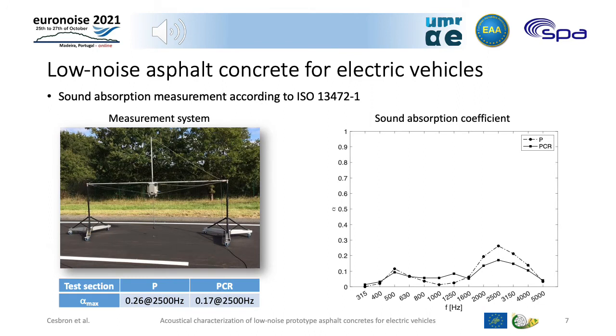Sound absorption was also measured by means of a system conforming to ISO 13472. On the right side you can see the sound absorption coefficient in 1/3 octave frequency bands. As you can see, the sound absorption coefficient was quite low for both prototype test sections, with a maximum value of 0.17 and 0.26 at 2500 Hz for PCR and P respectively.